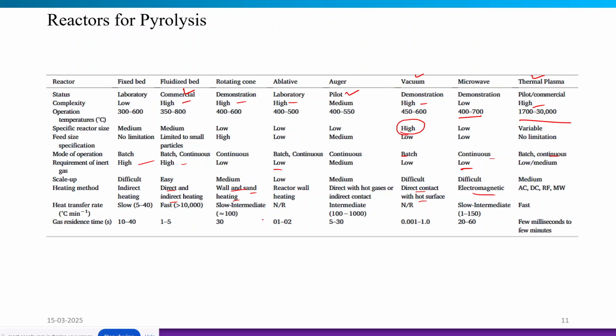The rate of heat transfer is highest in the case of the thermal plasma, and intermediate in the case of the microwave. It is very slow in the fixed bed condition, and in the fluidized bed it is also faster. Gas residence time in the thermal plasma takes a few milliseconds to a few minutes, but in other cases the maximum time is for the auger reactor, because it takes seconds, like 30 seconds, and in the fixed bed condition the gas residence time is higher. So you can go through this comparison table so that you can select which reactor you should use depending upon your process conditions available.